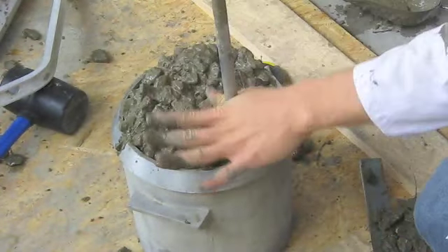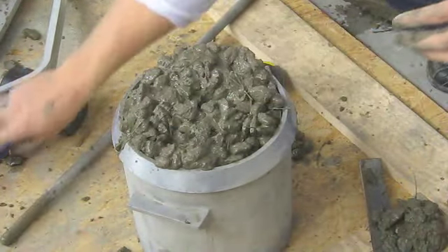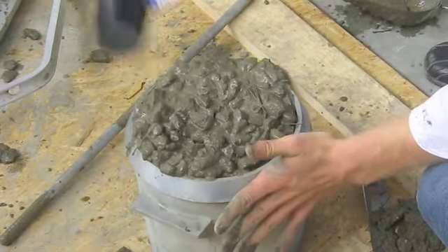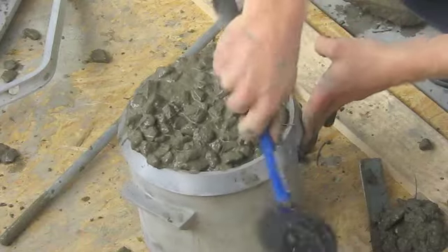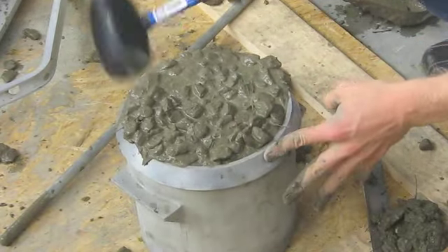When you finish rodding the specimen, you want to take your rubber mallet and knock the side of the canister 10 to 15 times. This should actually be completed for each lift. When this is complete, take your tamping rod and screed off the top.